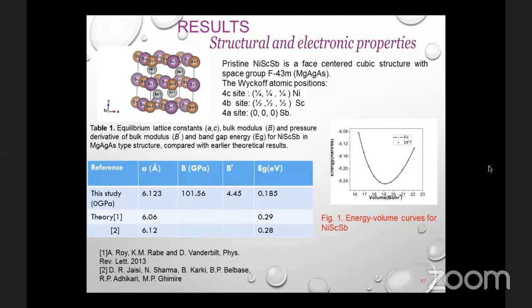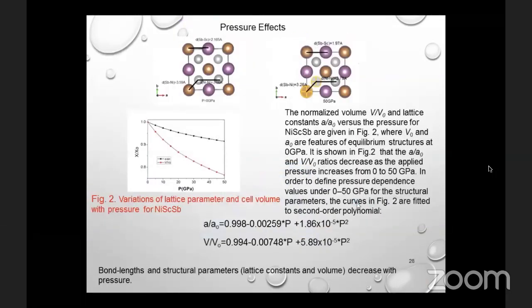Optimized parameters of NiScSb, such as lattice parameter, bulk modulus, and derivative of bulk modulus, were calculated by minimization and full relaxation of the unit cell. The obtained ground state properties are given in table 1, and the energy volume curve for the optimized crystal structure is also given in figure 1.